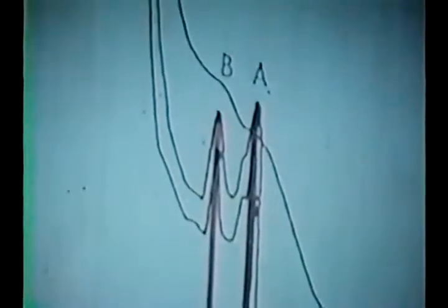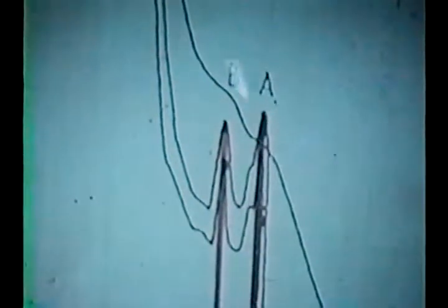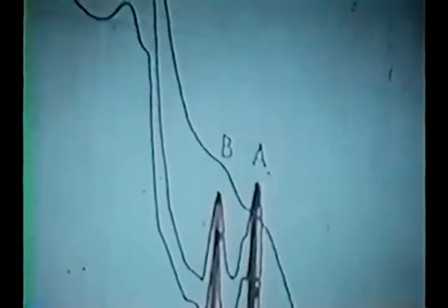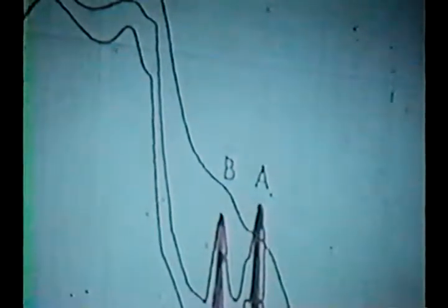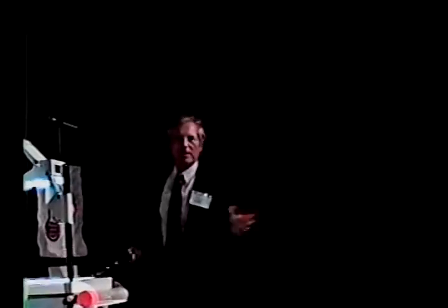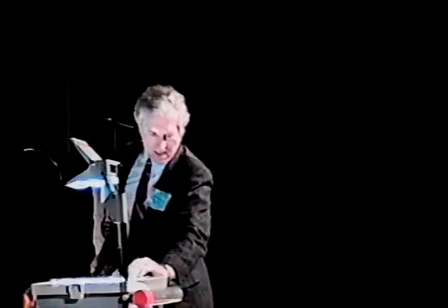When one introduces these intercalating ions, then one obtains the spectrum shown here, and that spectrum shows large absorption but disappearance of these transitions into the empty band. This is interpreted in the standard moly disulfide solid state literature as follows. You fill those empty states of molybdenum disulfide with the electrons coming from the intercalated ion, and then those states are pumped into higher states with low energy that is responsible for this large background, but because they are filled, the transition into those states does not occur. And in fact, studies have been made with sodium intercalated and the whole concentration range was covered. Now what happens in the real catalyst that we have?